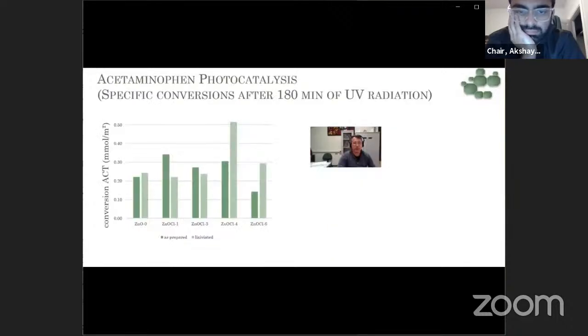photocatalysis. We have chosen the photodecomposition reaction of acetaminophen to understand the effect of chlorine segregation on ZnO. After 180 minutes of UV radiation, we have here the specific conversion, and for two conditions. The first condition is the as-prepared powder, and the second condition is for powders lixiviated with water.